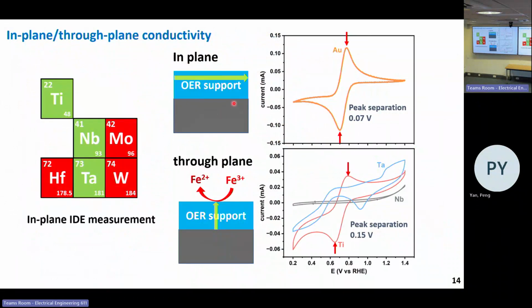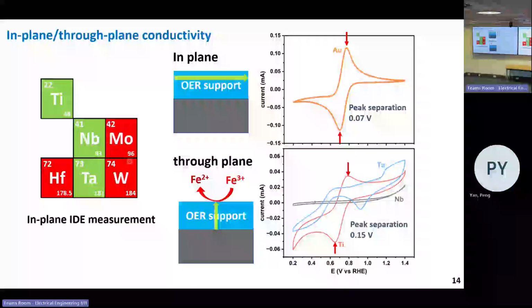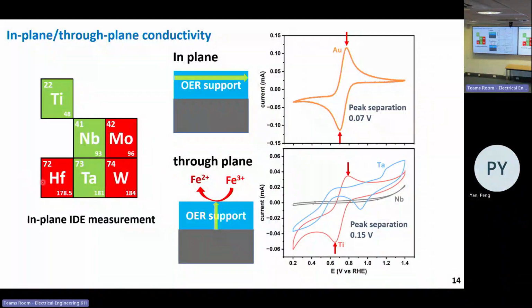So this interdigitated electrode was used to measure the in-plane conductivity, and it's safe to rule out molybdenum, tungsten, and hafnium. However, the through-plane conductivity is more relevant to the activity of iridium.